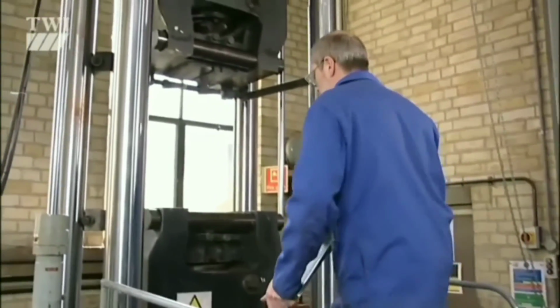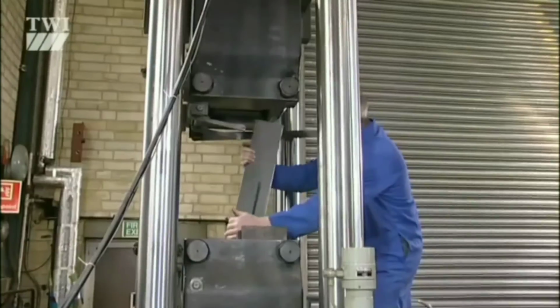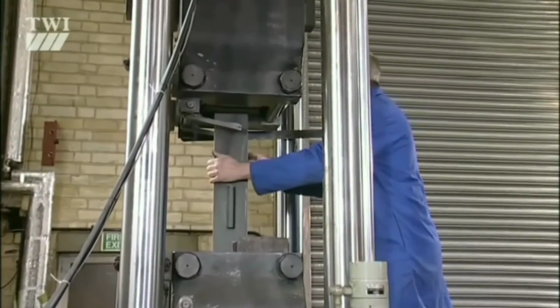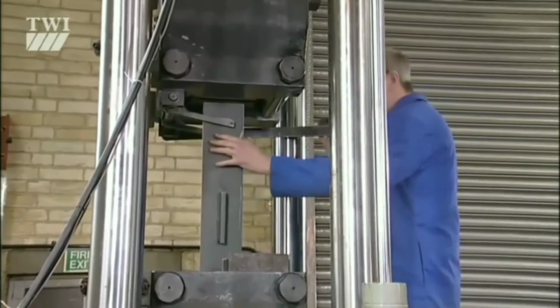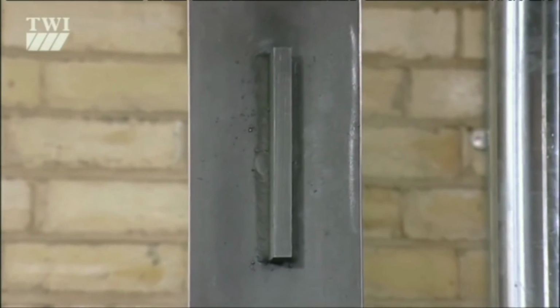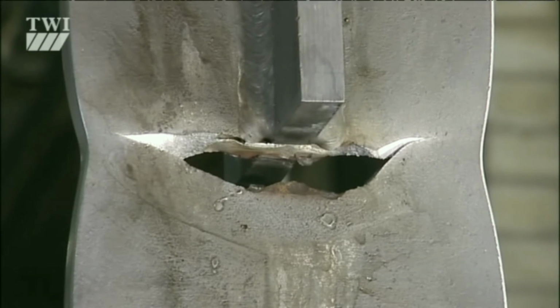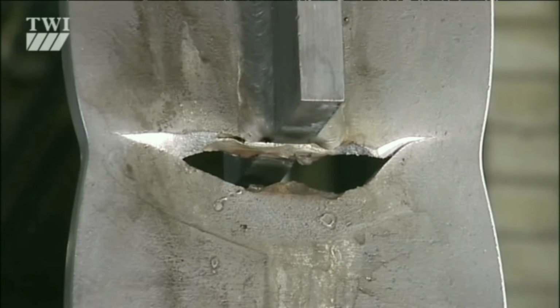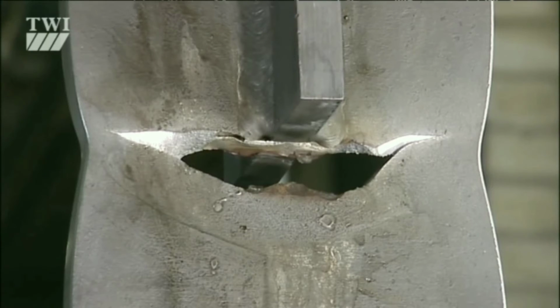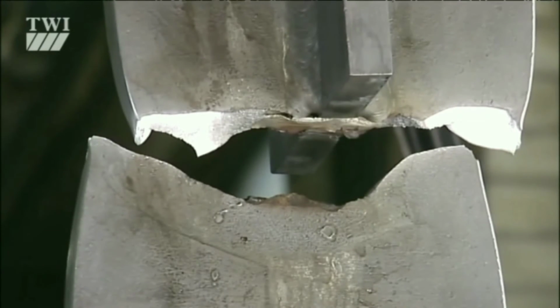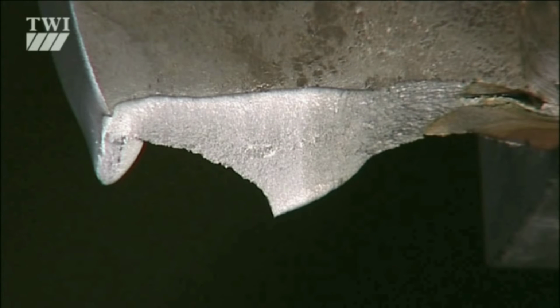Here we use a flat plate in simple tension with attachments on either side. The longitudinal fillet welds contribute little, but we'll see they pose a significant threat to the fatigue life of the specimen. But first, a simple tensile test. Elastic deformation is followed by plastic deformation. Necking becomes evident and ductile rupture occurs at a load corresponding to the material's tensile strength, and it leaves a characteristically irregular fracture surface.